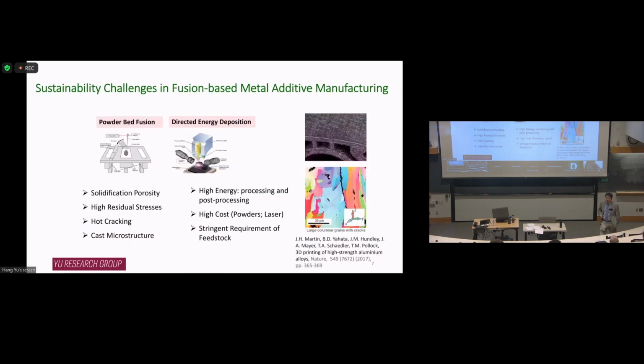It's pretty powerful, but it's not perfect, right? We have a lot of challenges now, actually. Because you have a small molten pool and rapid solidification, we're always suffering from solidification porosity. You have such a high thermal gradient, we're suffering from high residual stress. And for some alloys, so-called non-weldable alloys, you have hot cracking problems, right? And of course, this is a high energy process. You need to melt the material, so you need to heat it above the melting temperature. A lot of very high energy supply.